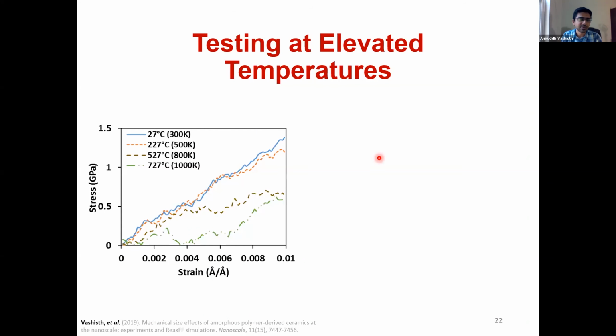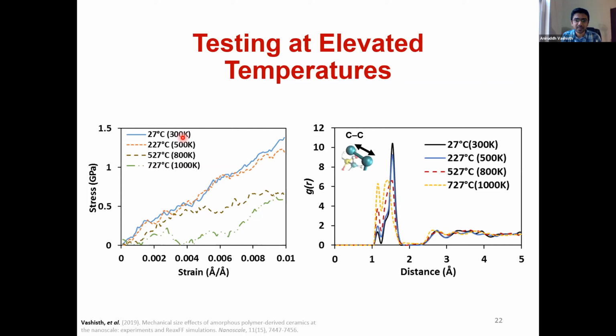So with this, we were pretty confident, and we went forward and did some virtual testing at elevated temperatures as well. And I will note that all these simulations were done in inert atmosphere. So they did not have any oxygen or water molecules present, which would be present in a real world scenario. And you can see we did some RDF, radial distribution function calculations, where you calculate the probability of seeing two carbon atoms close to each other at a particular distance. So this peak, which corresponds to the carbon-carbon single bond, sees a sharp decline as you increase the temperature, whereas two other peaks start to increase. And this is because as you increase your temperature, you're also aiding formation of carbon double bonds and carbon triple bonds. So this was a very interesting observation from the simulation as well.